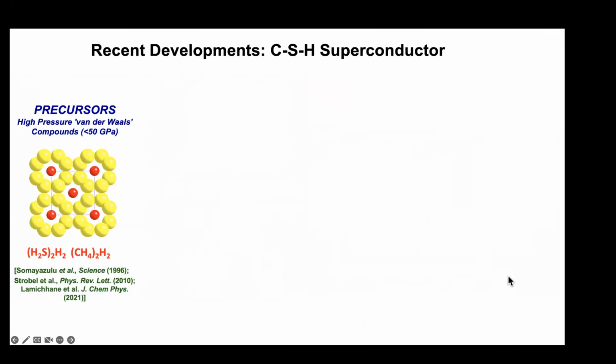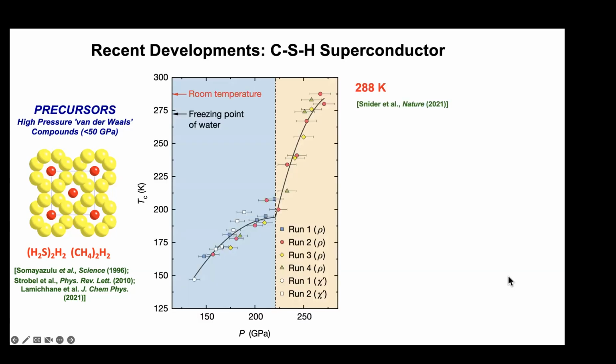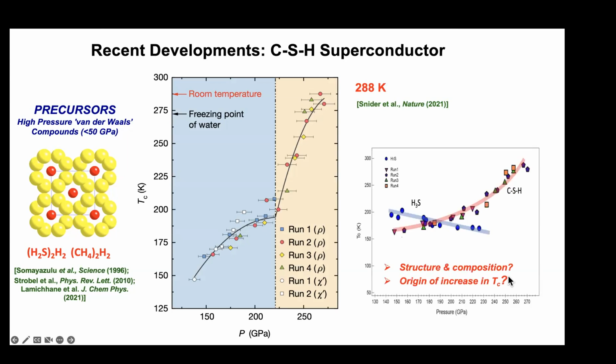So now I want to turn to some recent developments in ternary systems, starting with the CSH superconductor. As I mentioned, the precursors for this phase are these van der Waals compounds, and here's the beautiful TC plot from Ranga Dias's group, showing the TC reaching some 288 Kelvin at 270 GPa. One can also plot these data in a different way without the sudden onset, and more or less a continuous plot.